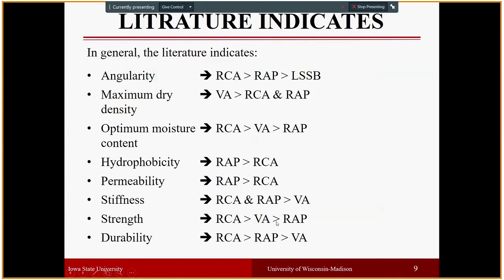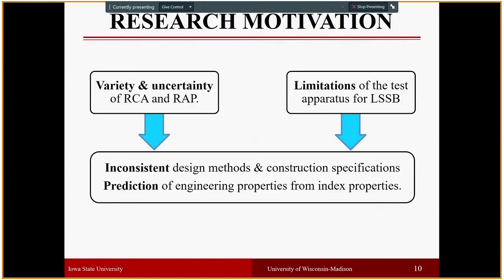And in terms of strength, RAP in the literature tends to have a little bit lower strength compared to RCA and VAs. And in terms of durability, RCA with freezing and thawing cycles keeps gaining strength. On the other hand, RAP and virgin aggregate had similar performance, or RAP sometimes had superior performance. I will be happy to provide more detailed information later if there are any further questions on the literature side. So the research motivation was the variability and uncertainty of these RCA and RAP materials.